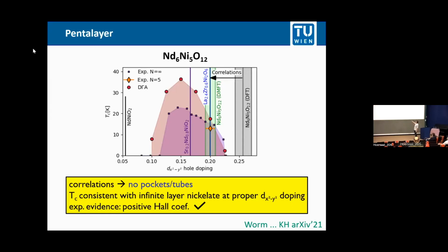And if you translate now the doping of the finite layer compound, 20%, and put it in here onto the previous experiment for the infinite layer nickelate with strontium doping, it's here, and you see the two agree extremely well within experiment if you adjust for the proper doping with or without pockets, and also with our dynamical vertex approximation calculation. So besides the DC, which is speaking that the pockets are really not there, there's another experimental evidence that